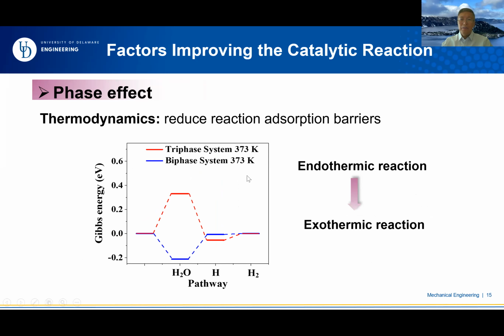Let me show you some simulation results that we got. From a thermodynamic perspective, again, it reduces the reaction adsorption barriers significantly. For example, for the water molecule adsorption on the catalyst, you can see in the biphase system this Gibbs energy changes from positive to negative. So it means this reaction happens spontaneously. And at the same time, the hydrogen molecule adsorption, or desorption, is more favorable for hydrogen desorption from the solid catalyst.